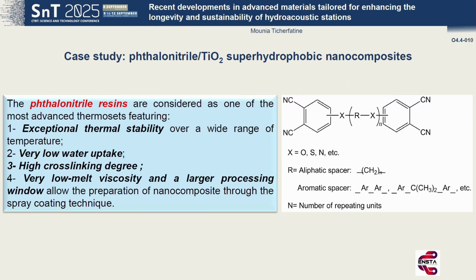So let's now move to a specific case study we performed recently. As I stated, this nanocomposite spray coating can be seen as the most adequate and cost-effective technique to achieve superhydrophobic coating. In this case, a new nanocomposite was developed from a high-performance phthalonitrile resin and silane surface modified titanium nanoparticles.